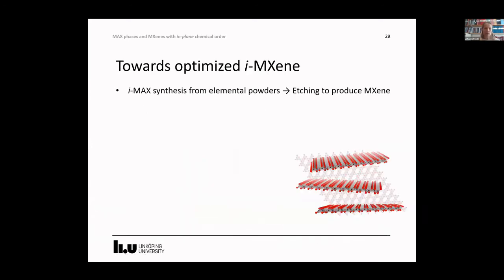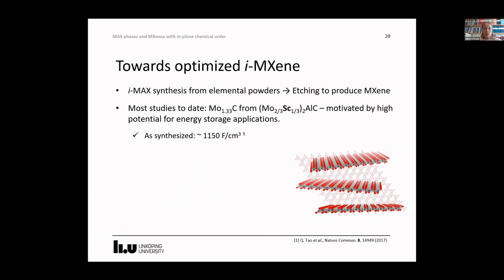So I tend to get back to the importance of MXene quality, which in my perspective is well-defined, homogeneous, reproducible material, of perhaps a rather low defect concentration. i-MAX synthesis to date has been based on elemental powders, but we're of course working on pathways for improving both the i-MAX quality as well as the resulting MXene quality. Most studies to date on vacancy MXenes are on Mo1.33C from the molybdenum scandium aluminium carbide, and this has been motivated by the shown high potential for energy storage applications.